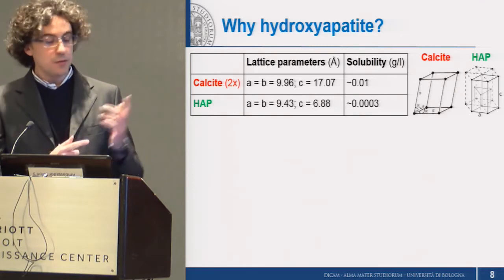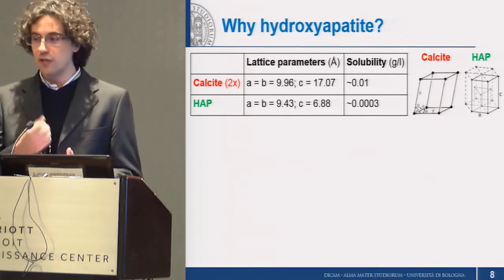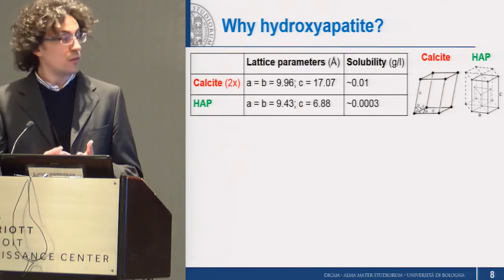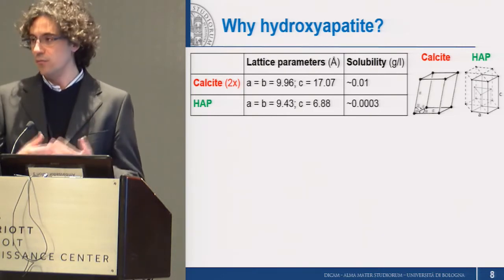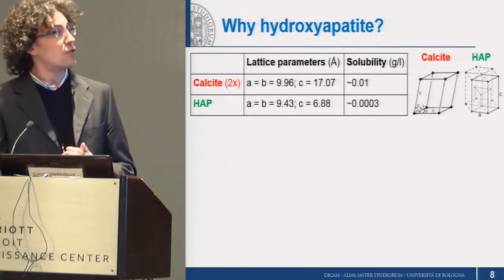First of all, because, as you can see, hydroxyapatite has a much lower solubility and a much slower dissolution rate than calcite, which of course is good to provide protection.